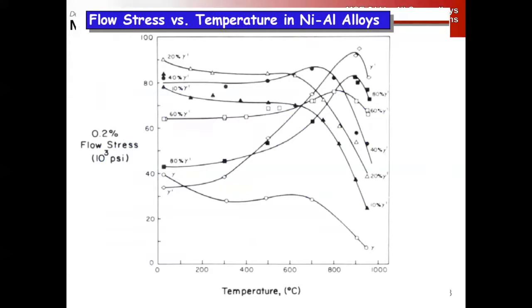We can look at this as a function of gamma prime fraction. So pure nickel 3 aluminum, pure gamma prime, you can see the huge increase in flow stress with temperature, whereas pure gamma definitely decreases. And if we look at about 80% gamma prime, which is our single crystal blade alloys, we have a huge increase in strength up to temperatures exceeding 800 C, and then they start to go down.